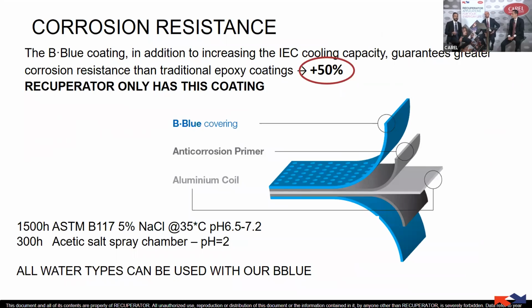And in this case, also this hydrophilic absorption coating has been seen to face it much better than the standard epoxy protection, because it's composed of two different layers. One is the primer, the other one is the active hydrophilic layer, and both of them are able to face the corrosion and resist different types of water. And we can reach plus 50% of resistance to corrosion, higher than the standard epoxy protection.